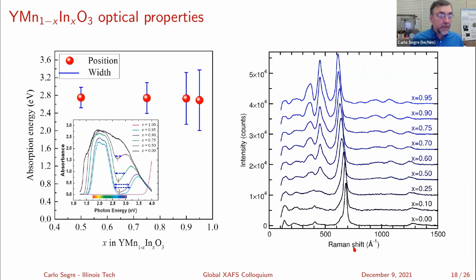And I have some slides that I actually didn't include. And exactly, the correlations have to be there, and XAFS doesn't require it. So if you have uncorrelated displacements, where, for example, it's not ferroelectric or ferromagnetic, where everything is off-centered in the same direction, it's just going to look like a bigger sigma squared, right? And that's really what's happening here. But my guess from our experiments with the zinc sulfide and the cadmium sulfide is that these structures will relax in a few unit cells. That's my guess. But we didn't really speculate on how big the nano domains can be.